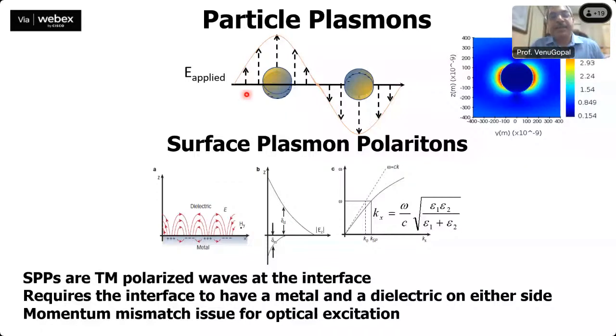So we can also have these so-called surface plasmon polaritons, where you have an interface of an epsilon positive material and an epsilon negative material. So we solve Maxwell's equations with the boundary value problem, the usual thing which we use for Snell's law, right? In the Snell's law derivation, we look at how much is the reflected and how much is the refracted or transmitted beam. But in this case, we ask a question like, is it possible to have a solution to the problem where there is a wave which is propagating along the interface direction?